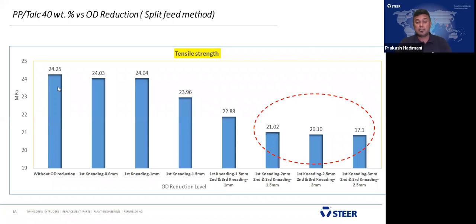First we'll talk about PP talc, 40% weight pigment. We use 40% talc, with no OD reduction here, using the split feed method. We observe the tensile strength, a mechanical property. Without OD reduction, we are getting 24.25 megapascal in tensile strength. In the first kneading section, we reduce 0.6 millimeter per side. At that 0.6 millimeter per side, there is no difference in the tensile strength.